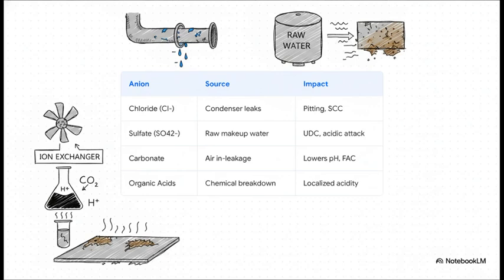Then you've got sulfates. These often sneak in from raw makeup water, or maybe leaking chemical regenerants from your ion exchangers. Sulfates are notorious for accelerating acidic attacks and under-deposit corrosion. Carbonates and carbon dioxide, they usually show up via air in-leakage. Once they're inside, they lower the pH in those early condensates inside turbines, totally setting the stage for flow-accelerated corrosion. And finally, organic acids. These are kind of ironic because they often come from the thermal breakdown of the exact water treatment chemicals meant to protect the system, ultimately leading to localized acidity under high pressure.